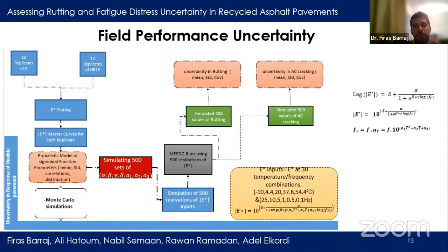Now, the framework used to assess the uncertainty in field performance of both mixes, the control HMA and RAP mixes, was based on the variability in the dynamic modulus master curves as shown. Firstly, 12 replicates of each mix type were tested, and the measured data was used to develop 12 dynamic modulus master curves using the sigmoidal models expressed by the displayed equations.